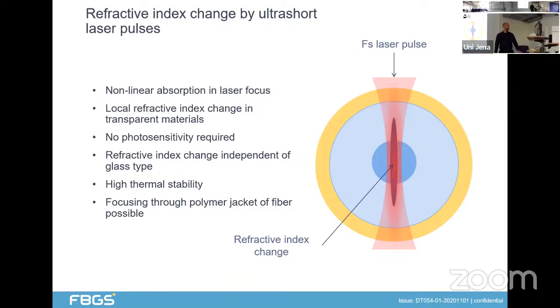The second method I will talk a bit more in detail about is using a femtosecond laser to write the fiber Bragg gratings inside. Here we use the nonlinear absorption process in the focus of the femtosecond laser. That means the local refractive index is changed in the transparent material. The good thing about that technology is that we don't need any photosensitivity of the fiber core. So that means it is independent of the type of fiber. Standard germanium doped fibers can be used, which are photosensitive, but also pure silica core fibers, which have no photosensitivity.